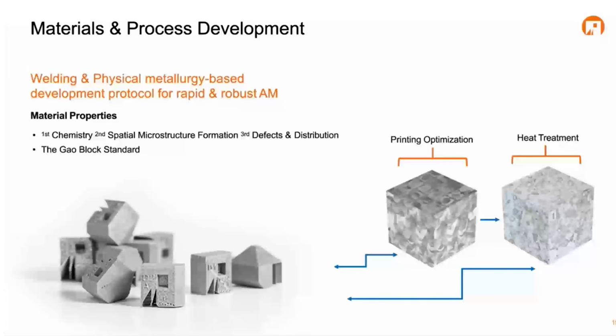That's the aspect of the weld pool and the processing parameters, getting the right ratio of velocity, which controls the solidification as well as the temperature gradients, along with the power of the laser itself. That's what we're looking to do to get the right microstructure and maybe secondary phase formation as well.